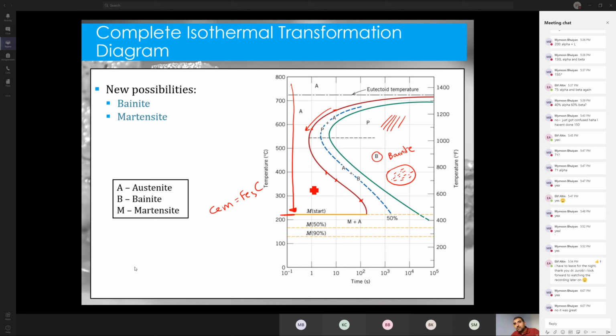the only thing that can happen is a transformation that does not require diffusion. So there are transformations that happen that do not require diffusion, that do not require the atoms to jump from their positions. Rather, what happens is we call it a shear. There is a tiny shift in atomic positions that happen. All the atoms move at once, and that shifting changes the crystal structure from one to another related one. So what happens here is the FCC, or the austenite, or in this diagram they also show it as A. So this is A for austenite, okay? Or gamma. It transforms to M, which stands for martensite. And martensite has a different crystal structure that we haven't learned about, but it doesn't matter. It's called BCT, body center tetragonal. But for all we care, it's just another crystal structure.